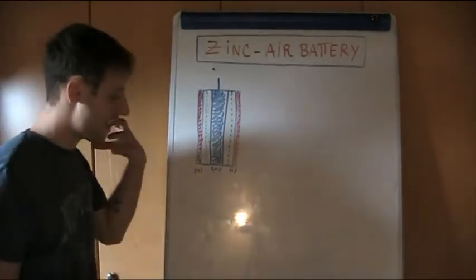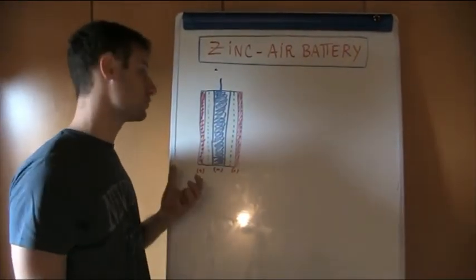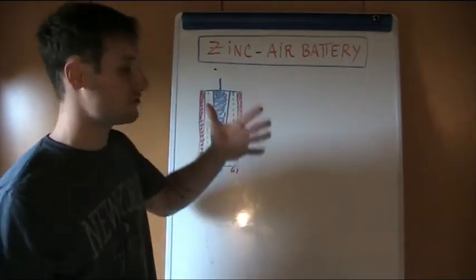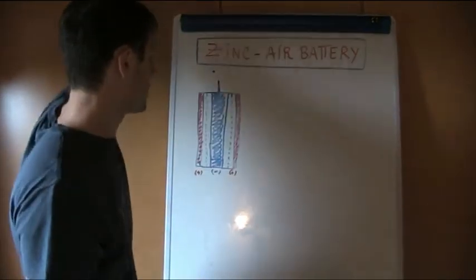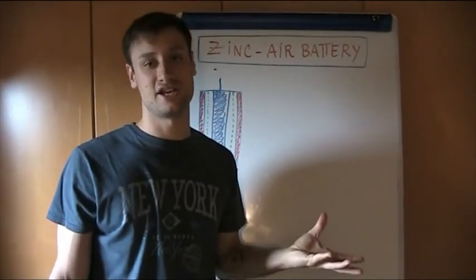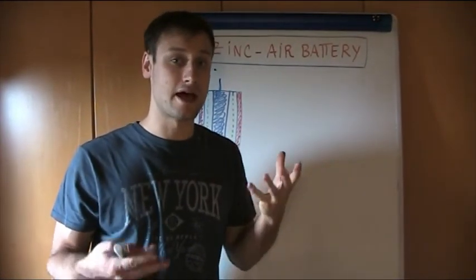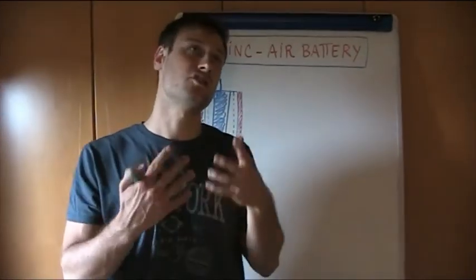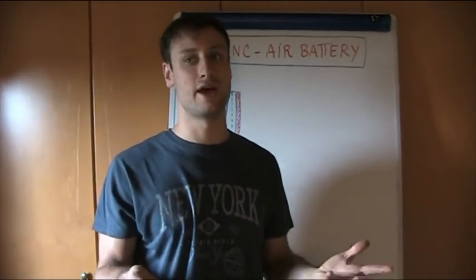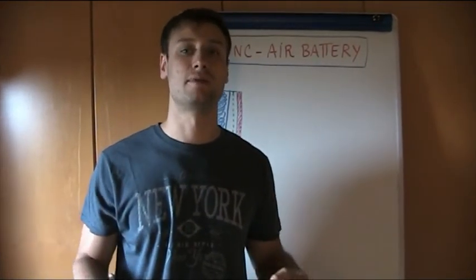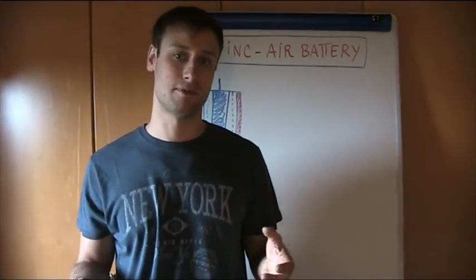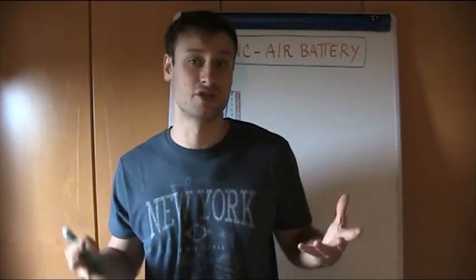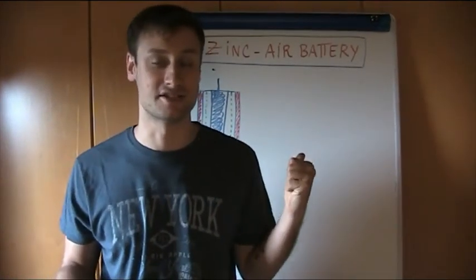What does it mean? When we have consumed our zinc, so when it has been totally, or at least for the major part, converted into zincate and the zinc-air battery is approaching its death, we just need to substitute this electrode with a fresh one with new zinc. And so in a specific process we are able to restore the working of the battery just by replacing one of the two electrodes. So it's not a real recharging in a conventional way by applying a potential or a current, it's a recharging due to a mechanical action. But it's a smart way to overcome all the different problems connected with the battery redeposition mechanism, even if obviously we are wasting money and matter since we need to replace the zinc electrode.